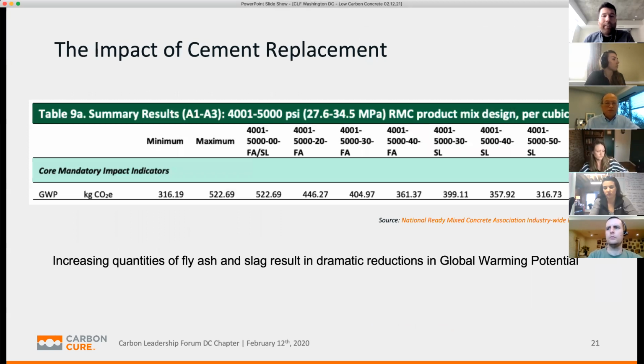And just again, referencing the Ready Mix Concrete Association, this is an example here of what the industry average looks like. So I think Teck's example there was showing you that for that 5,000 PSI mix, it was something around the order of 270 kilograms. In this case, what the National Ready Mix Concrete Association is showing us is that 5,000 PSI mixes typically range between 316 and 522 kilograms. So you're seeing the minimum and maximum there on the left. The industry average is taking into account different producers in different regions that have different energy grids, that have different standards and practices.